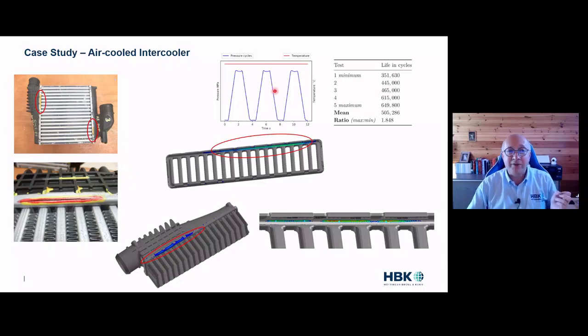And we can see they've done 5 physical tests here. The lowest life was 350,000 cycles to failure. The highest one was 650,000. So the average life is about 500,000 cycles, and there's about a ratio of 2 between the highest and the lowest. And we've also done finite element analysis to find the hotspot and to calculate the life based on that.